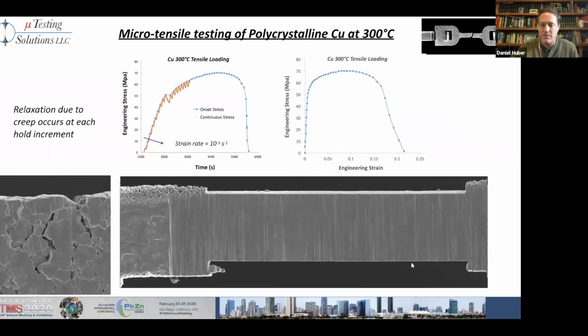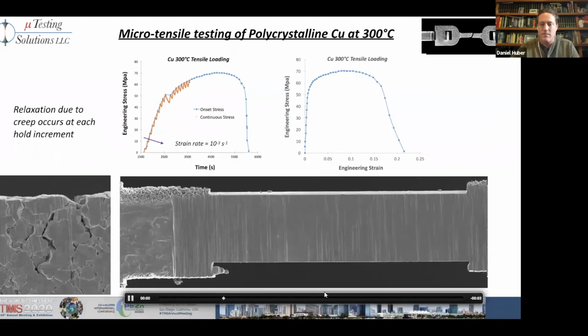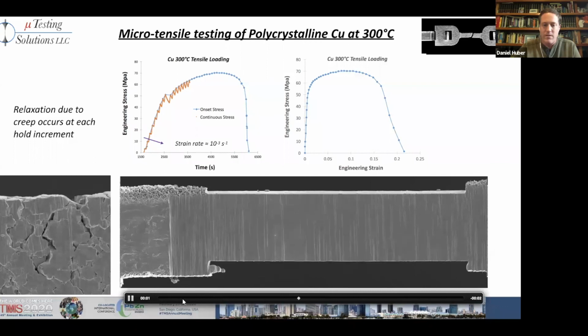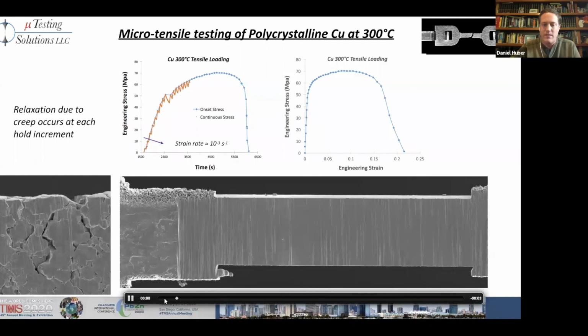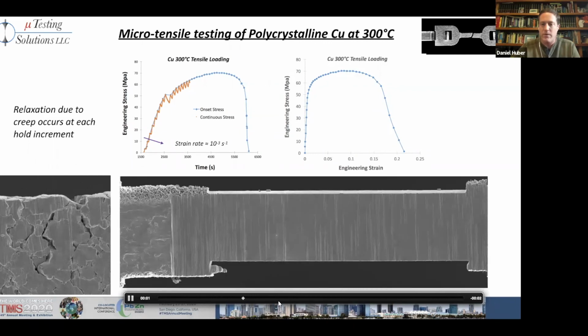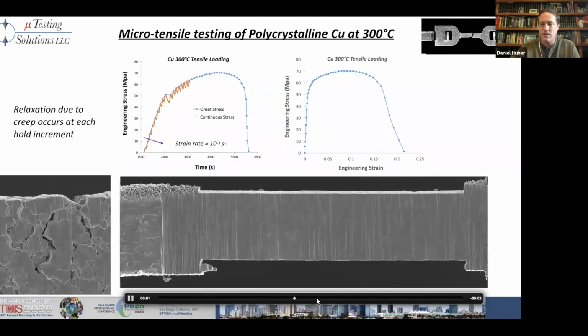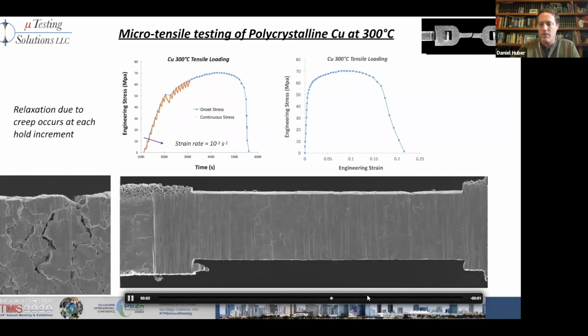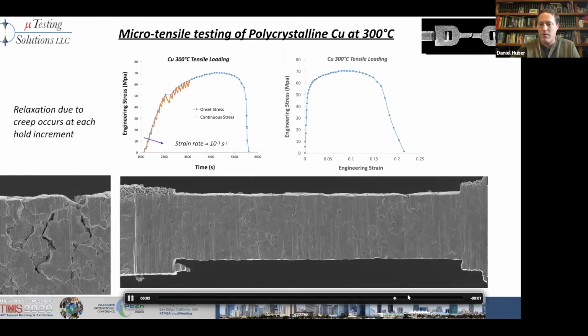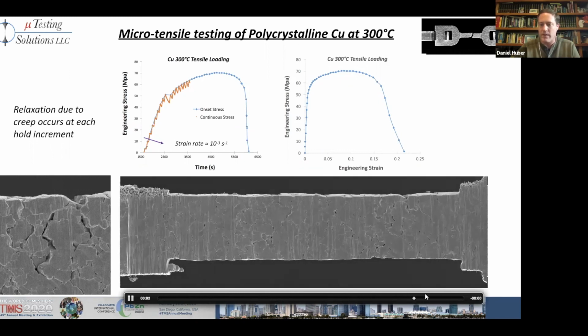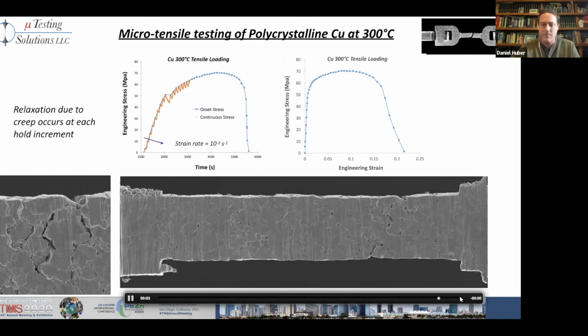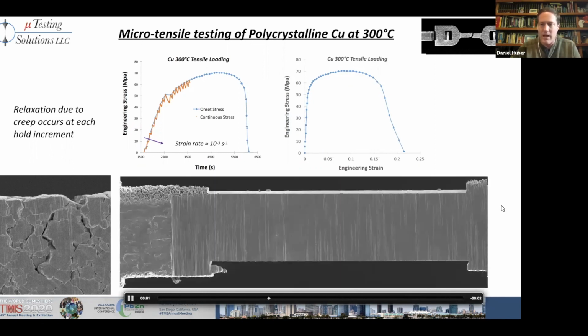Here's an example of, let's see if this will play here. This is a copper material that gets pulled and stressed and stretched all the way to failure here. You actually start to see all the grains start to come apart. The material will neck down and then ultimately break. And so this is, again, all happening on a size scale of only a few tens of microns here inside of the scope.